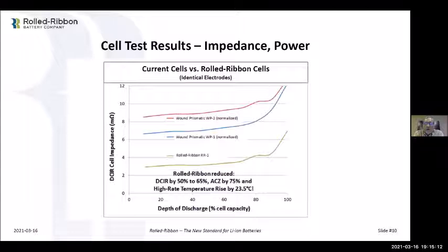Then the foil goes through a calendaring process. So you have a certain coat weight you put on there, and then they call it press density. And you go back and calendar it to increase the volumetric density of the material without adversely affecting the morphology. But that's standard process. You do that no matter whether you have a cylindrical, pouch, or prismatic cell.